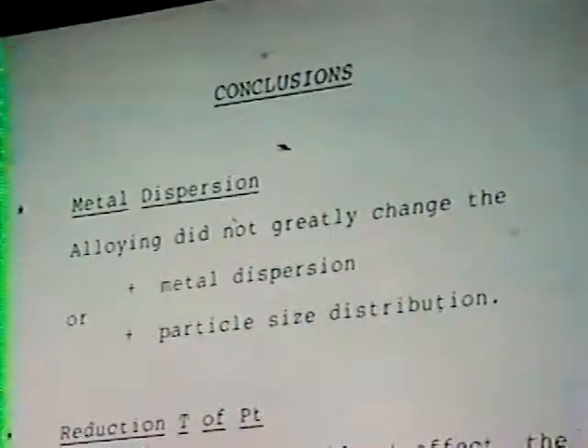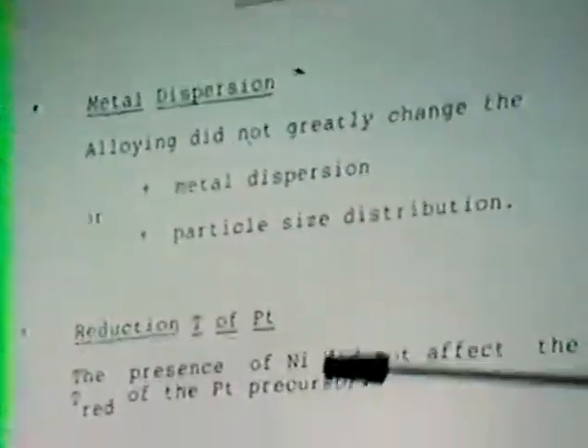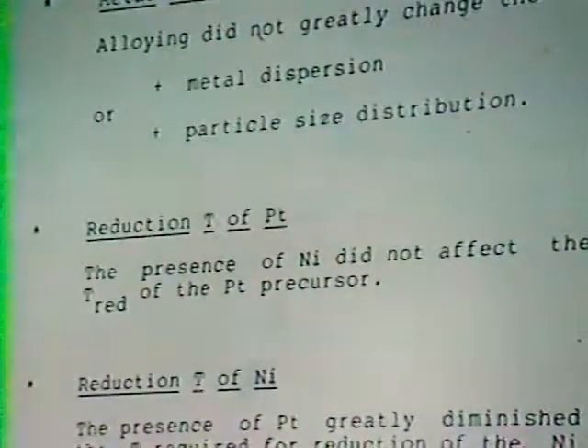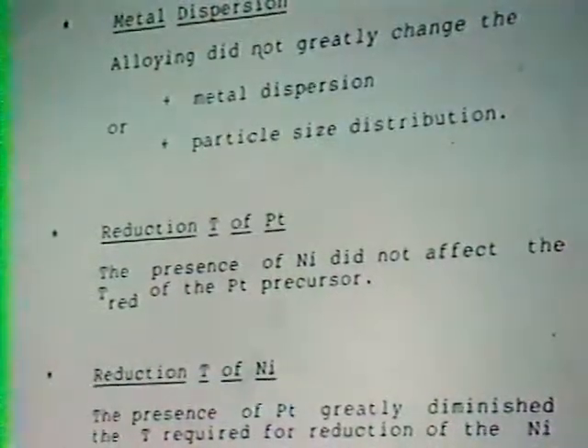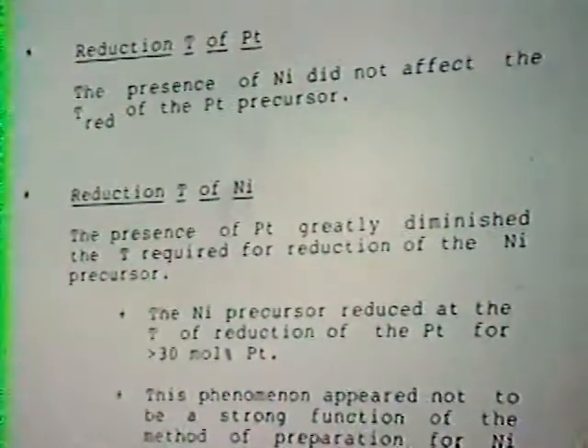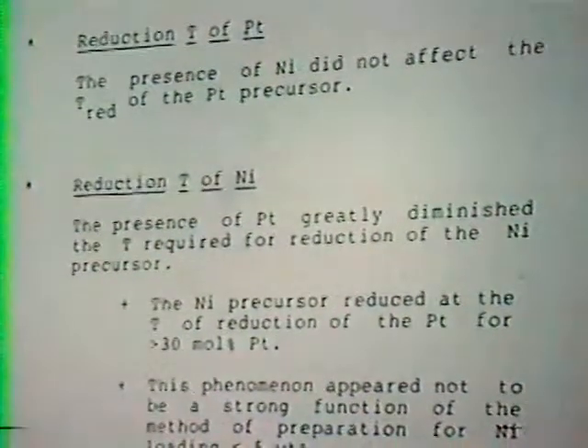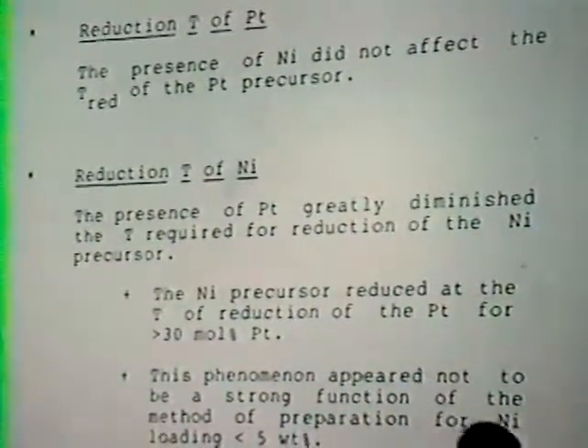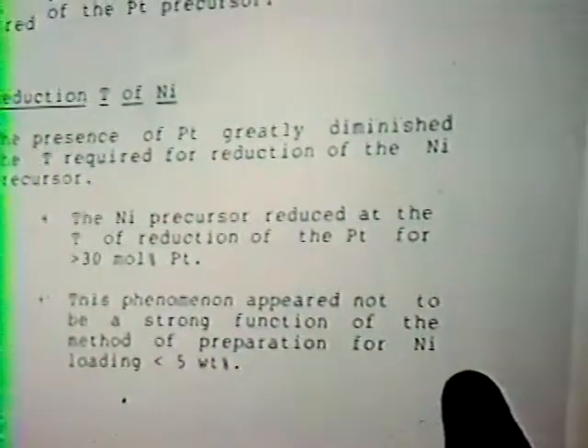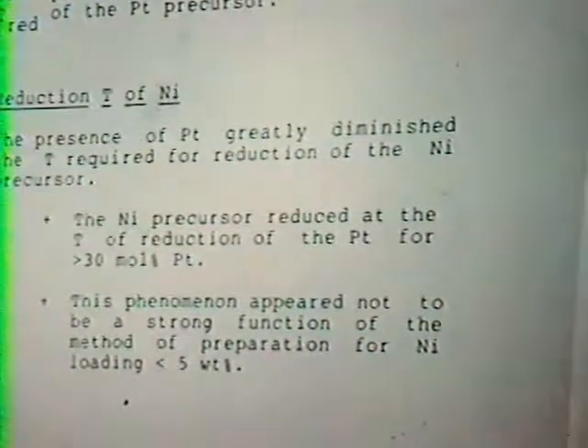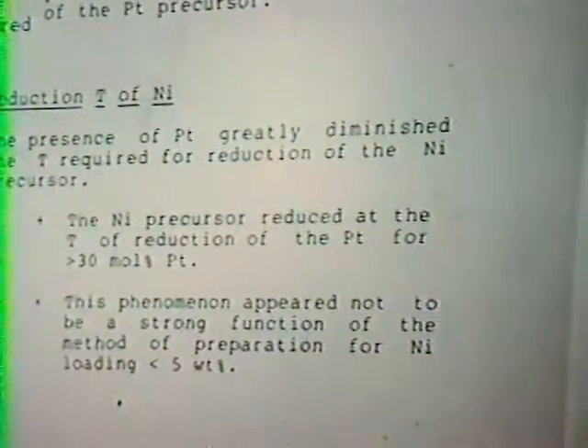Finally, conclusions. Metal dispersion is not greatly affected by the presence of platinum. It doesn't decrease or anything like that, the dispersion of nickel. Reduction temperature of the platinum is not affected. I'm talking about platinum precursor now. However, the reduction temperature of nickel is greatly affected, and for greater than about 30 mole% platinum, you can, of course, reduce the nickel at the temperature of platinum. Of course, I'm talking kinetics here.